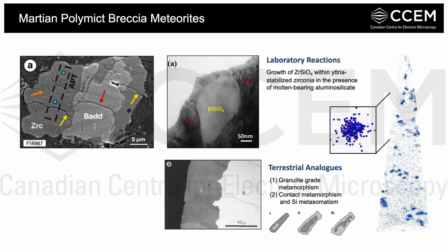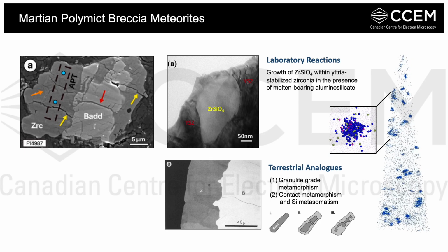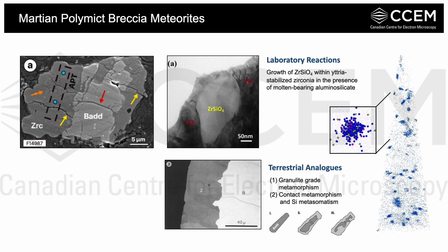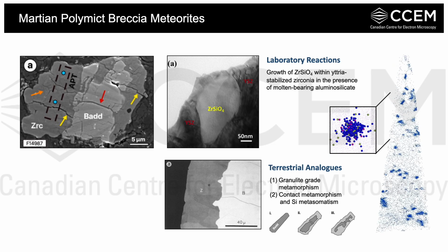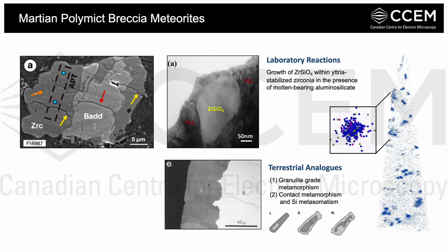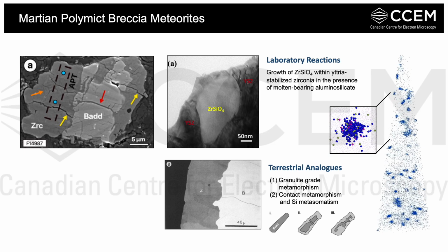First, it suggests that we had a rapid replacement reaction from baddeleyite to zircon, and this must have happened in a short time interval, or else we would expect that this excess iron would be removed from our system instead of being incorporated and trapped in the zircon.